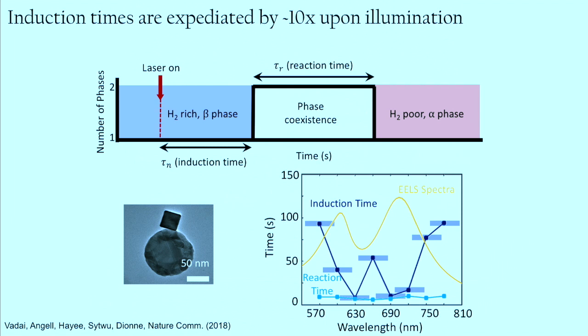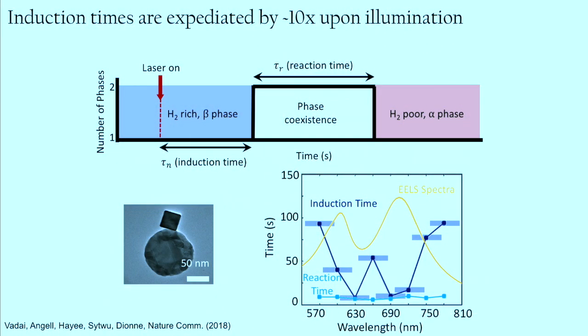So how do these times vary as a function of illumination wavelength? Well, if you look at the induction time shown in blue, you'll notice that generally it takes tens or hundreds of seconds for the transformation to occur in the dark. When we turn the light on, it also takes about that long unless we're at two very particular wavelengths, where we can expedite the kinetics by about 10x. So we expedite the induction time to only take on the order of a few seconds when we're at two wavelengths that correspond to the resonances, the electromagnetic resonances of this antenna-reactor pair.